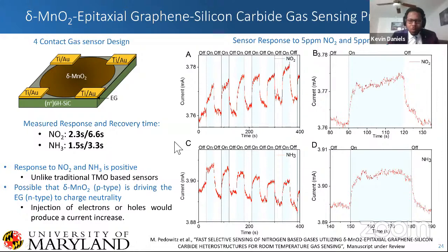Now, there's a few reasons why we think that might be the case. We think that it's possible that the manganese dioxide is driving the graphene to charge neutrality, which would mean that injection of electrons or holes from these species would cause an increase in current. Now, it's also important to note that there's a positive trend here for the NO2, and for the NH3 there's a negative trend. So this is something that we're still investigating, whether we're actually having this kind of depletion region of charge neutrality as a result of these materials, or if it's some other structural changes that are happening that's causing this effect.